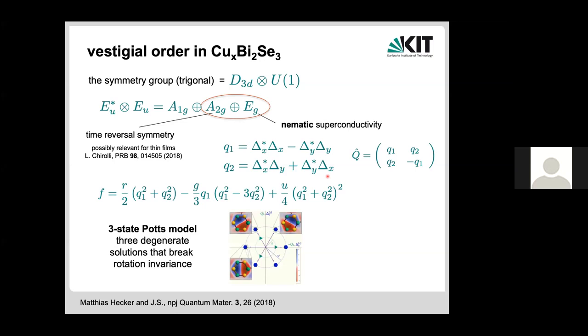Now, the simple question, I bet you've thought hard about it, is: we heard Peter Armitage say that terahertz spectroscopy is a very powerful way of looking at a superconductor. Wouldn't you expect that with these kinds of experiments, you can actually pick up directly that you're dealing with this kind of nematic superconductivity, and perhaps, when you are in a nematic phase without superconductivity, look at the fluctuations to learn a lot of interesting things? Well, in particular in this intermediate phase, but of course, keep in mind, you need to do a measurement in this specific sample within half a Kelvin. Of course, this is a very strongly fluctuating superconductor that fluctuates in a highly anisotropic way, and it must therefore have an anisotropic optical response, among others, of course.